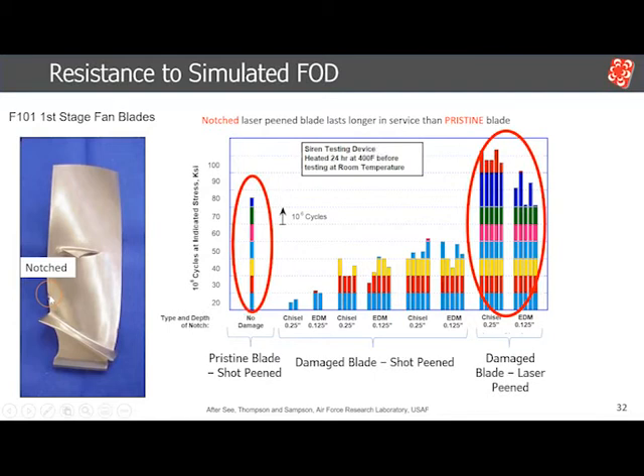The fact that we're generating compressive stresses delays crack initiation, as I showed in the previous example, and both crack initiation and crack propagation. This is how the first application of laser peening was able to get the life improvement for these blades. So again, in a simple way of looking at it, a virgin object damage is a notch, a high stress intensity factor location that goes through crack initiation and propagation. And that's how laser peening, by generating compressive stresses, can delay crack initiation and crack propagation, improving the total life of any component.